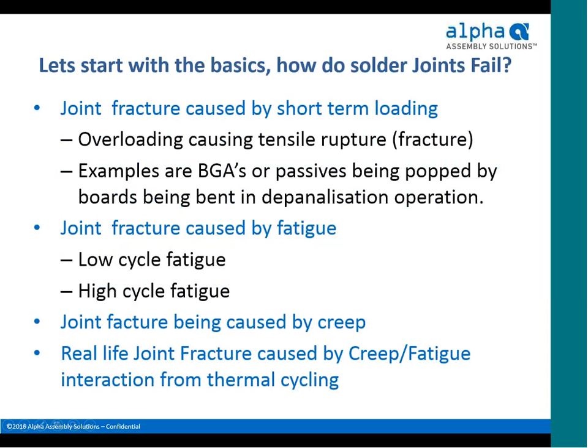So first thing we'll talk about is how do solder joints fail, right? Joint fracture can be caused by short-term loading. Any mechanical bond is going to have an ultimate strength that it's going to be able to hold. If you exceed that ultimate strength, you get fracture, tensile fracture of the connection.